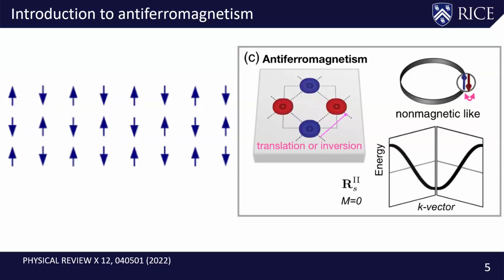In the case of a simple antiferromagnet, here I'm strictly talking about a simple collinear antiferromagnet on a simple square lattice, you would expect the magnetic wave vector to be a finite momentum transfer Q, because your unit cell has doubled in both the a and b directions. Looking at the spin wave or the electronic band in such a situation, you have translational invariance and rotational invariance, and you should expect the spin up and spin down electronic bands to be completely degenerate. Likewise, the spin waves, left rotating and right rotating, are also completely degenerate, so there's no difference, whereas in a simple ferromagnet the spin wave only rotates counterclockwise.